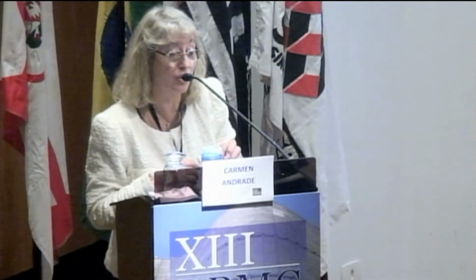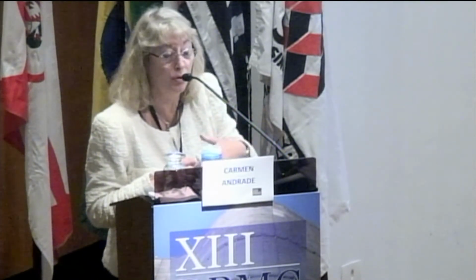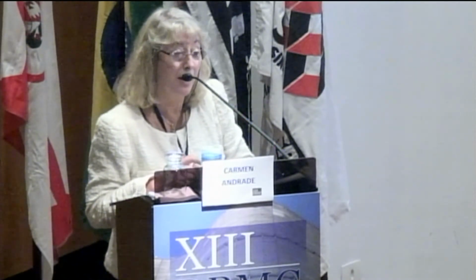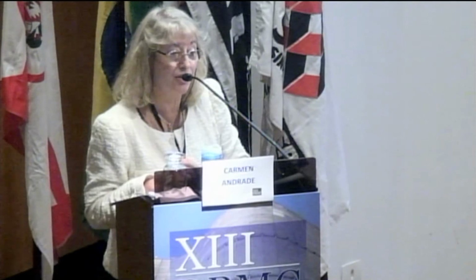Conservative for type 1 is almost 0, because there are some of them that almost don't have aging, because they are completely hydrated after the 28 days, and only when you have contact with the salt water, you have a refinement of the pores due to the precipitation of the Friedel salt. In that case, you may go to 0.05 or 0.1. And for type 3, a conservative value may be between 0.3 and 0.5, because CEM3 has a very high aging factor. You mean the binding of chloride? Well, stopping the penetration of chloride, so binding, yes, not allowing the profile to go ahead.